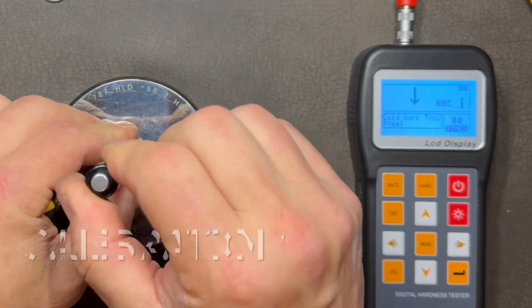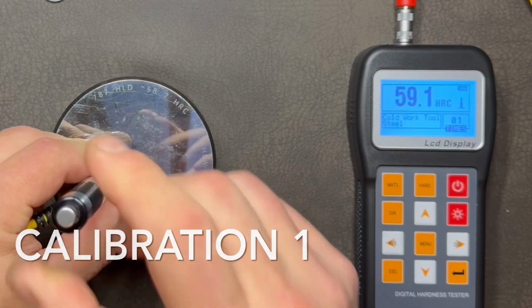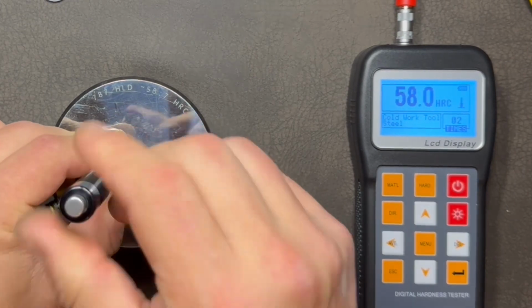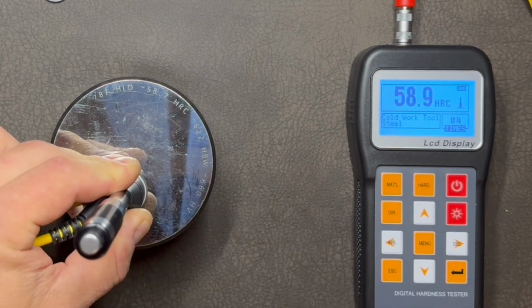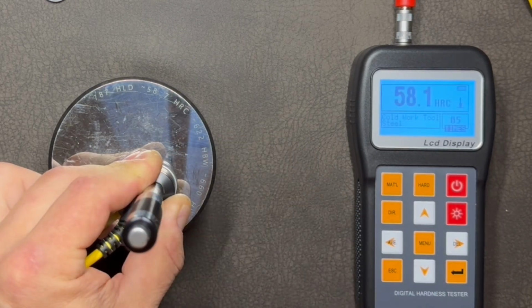I'll discuss why later. The tester I picked for my channel is a little different. It takes 5 measurements in close proximity to one another and then gives me an average. So when I calibrate or recheck my calibration, what I do is measure the hardness of that provided calibration block. And here it is. I'm striking it 5 times and it will give me an average. And the error is called zero shift.